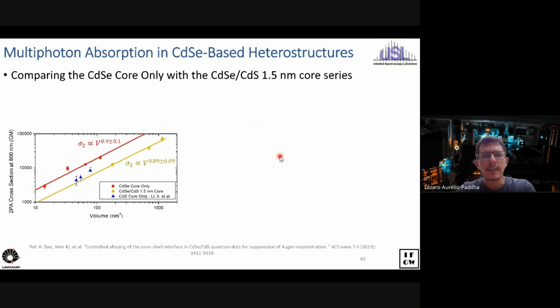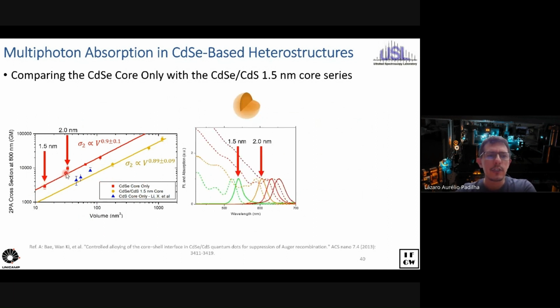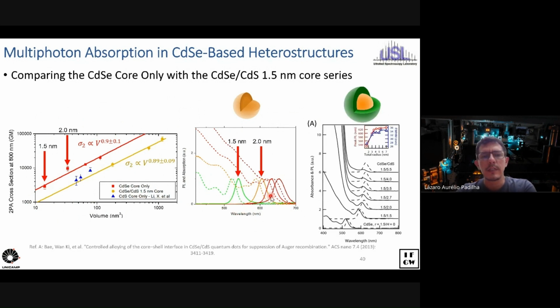So basically now we have all those results where we look at the data for the core-only and the core-shell quantum dot, and we see how it changes with the volume. They follow basically the same volume dependency, a nearly linear dependence. Meanwhile, to change the absorption cross-section by a factor of nearly 5, for core-only you really shift quite a lot the emission in the band gap. That's not the same for the heterostructure, because you keep basically the emission on the core, so you can increase your total volume by nearly an order of magnitude and change the emission spectra only very slightly.